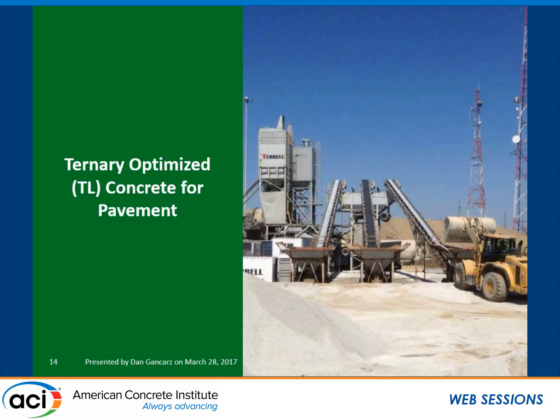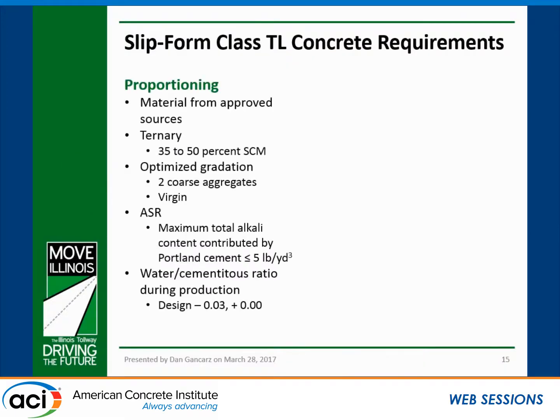So moving on to our pavement mix, what we call our ternary optimized Class TL mix for pavements. We have some more proportioning requirements. So again, the materials have to be from approved IDOT or Tollway sources. The mix is required to be ternary with 35 to 50% SCMs. You're required to have an optimized gradation, which requires 2 coarse aggregates, and they must be virgin. And then we also have an ASR requirement of less than 5 pounds per cubic yard on alkali loading. And then again, the water cement ratio tolerance during construction.